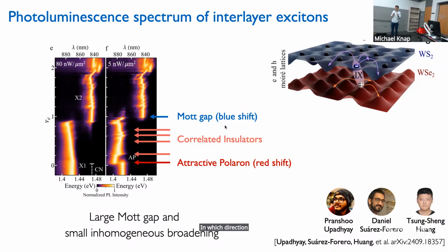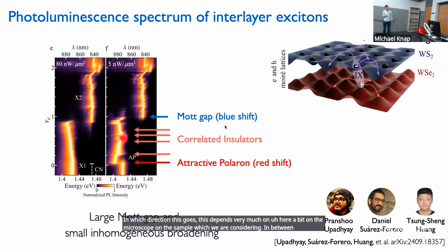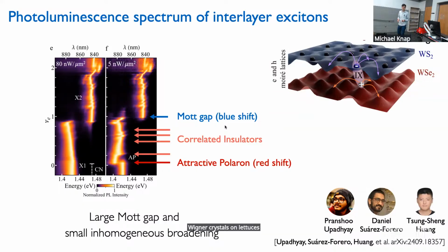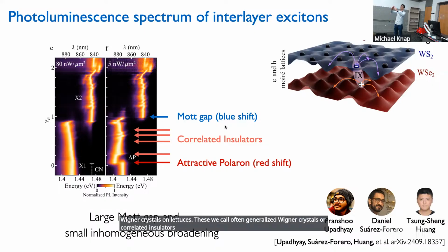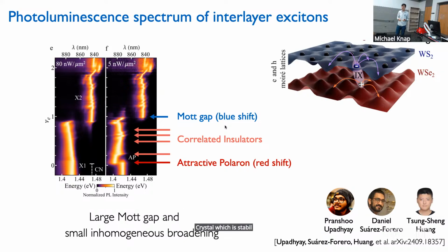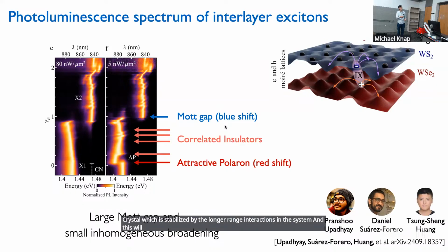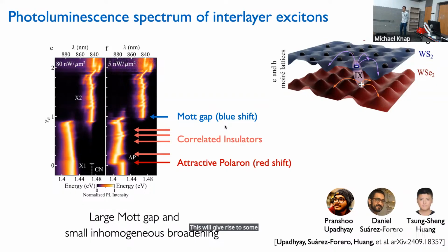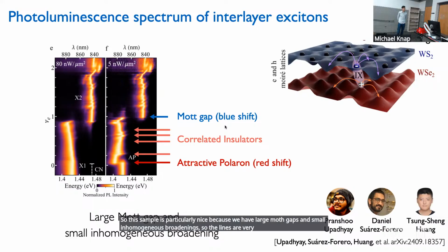In which direction this goes depends very much on the sample which we are considering. In between, I was saying that there's some squiggling going on. This is indeed structure which is important, and it's an indication of the formation of some Wigner crystals on lattices. These we often call generalized Wigner crystals or correlated insulators. For instance, think of the triangular lattice where on 3 sides I remove 1 particle, then I would have a honeycomb lattice left, and this would be a stable crystal which is stabilized by the longer range interactions in the system, and this will give rise to some squiggly structure in the response of the system. So this sample is particularly nice because we have large Mott gaps and small inhomogeneous broadenings, so the lines are very sharp in the response.